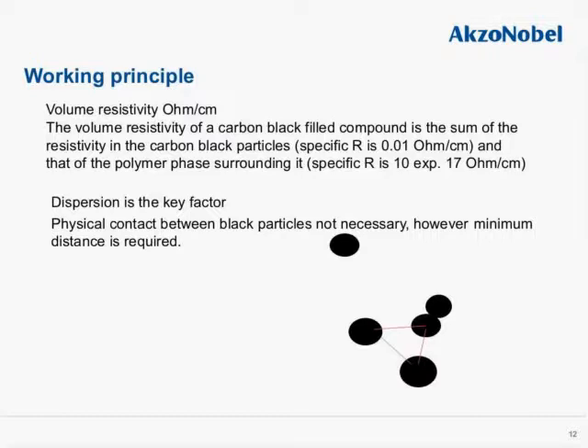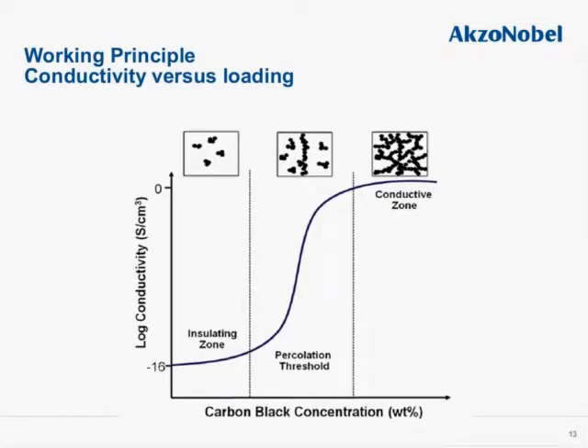So, kind of summarizing, Ketjenblack can turn a plastic compound into either a fully conductive compound or anti-static, just conducting electricity on the surface, and that depends on the concentration of the Ketjenblack as well as how well the product is dispersed in the final product. This brings us to the so-called percolation threshold, which is the lowest Ketjenblack concentration at which the end product becomes conductive. As indicated on the y-axis, we measure conductivity versus the concentration. Usually, the Ketjenblack requires a fairly low concentration, somewhere between 3 to 5%.